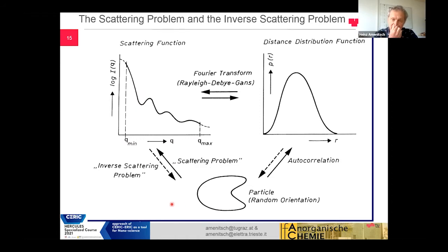And what you can do quite easily is go in this direction, calculate the pair distance distribution function, and try to interpret it, which already gives you quite a good insight about the structure, shape, and dimensions of your sample. And then you can also try to calculate the square root deconvolution and, in certain cases, also the electron density of the particles and the shape.